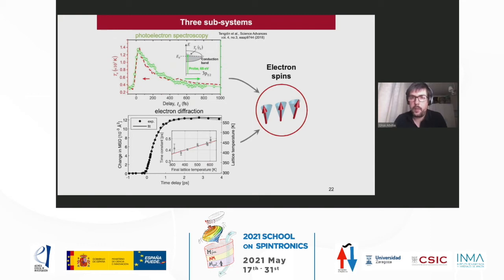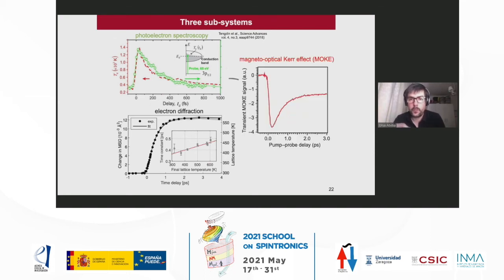Finally, the spin system. There is still no technique to directly measure the spin temperature, but you can use magneto-optical effects, like the Kerr effect, to measure the dynamics of the magnetization. For example, here is how the dynamics of nickel look using the magneto-optical Kerr effect.